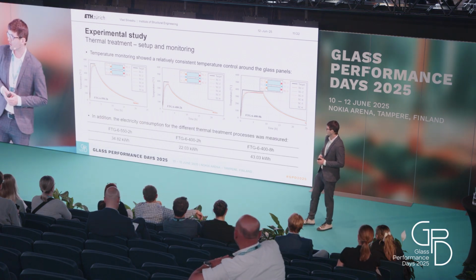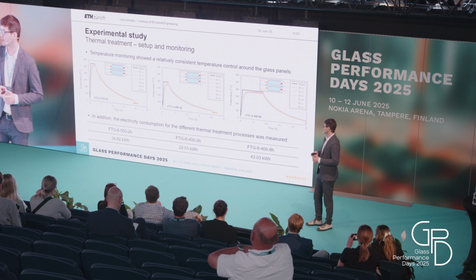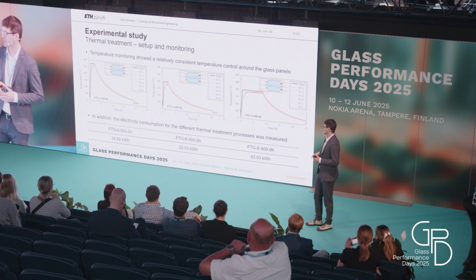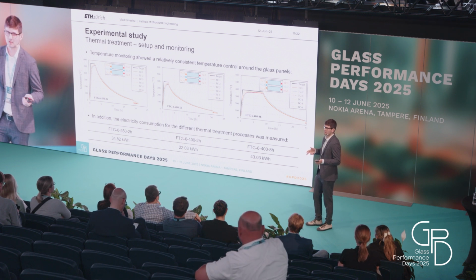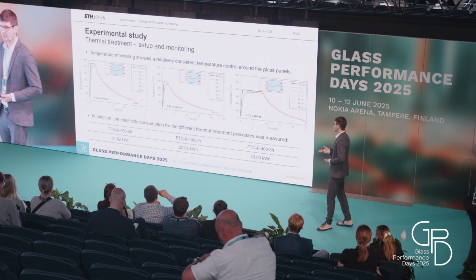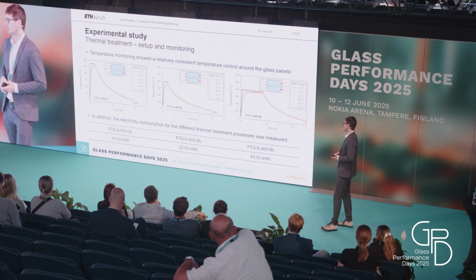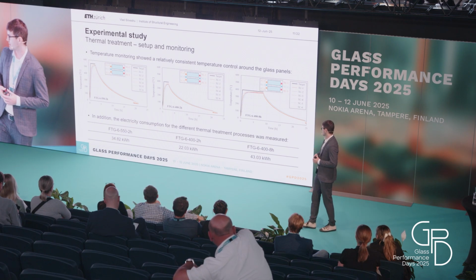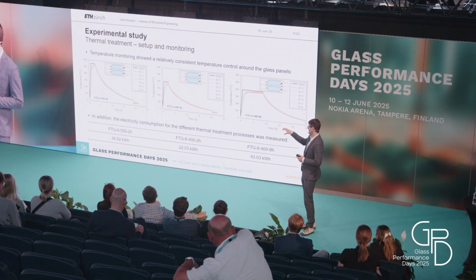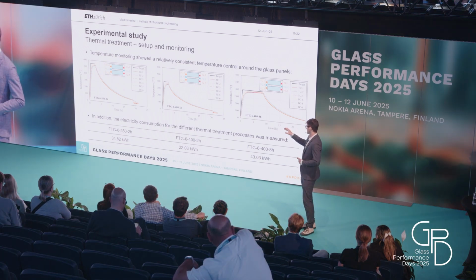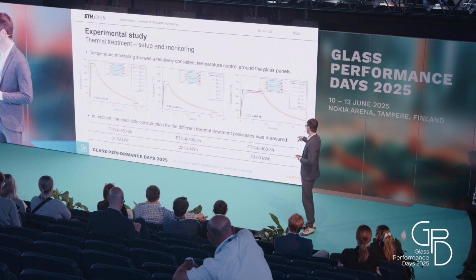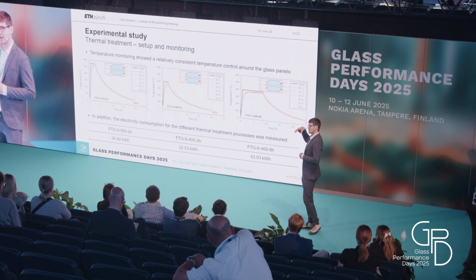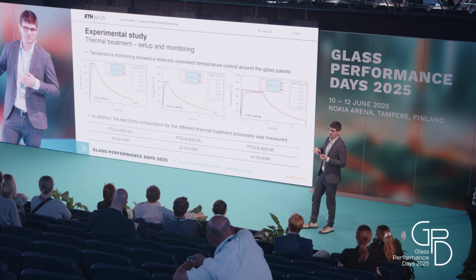And I also monitored the electricity consumption. The absolute values are, I think, not that relevant because the furnace is not optimized for this process. What's maybe interesting is that comparing the treatment at 550 degrees for 2 hours with the one at 400 degrees for 8 hours, we can see that holding the temperature at the lower level for a longer duration actually needs more electricity than the higher temperature for the shorter duration.